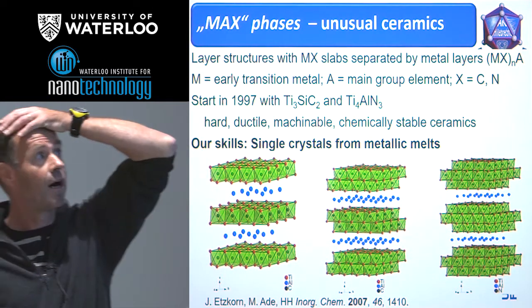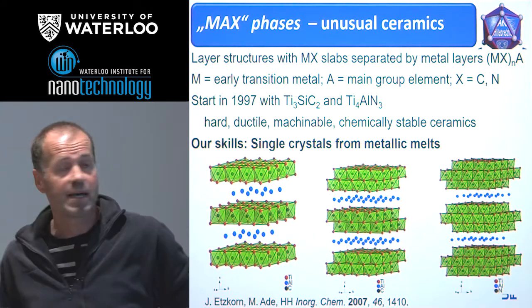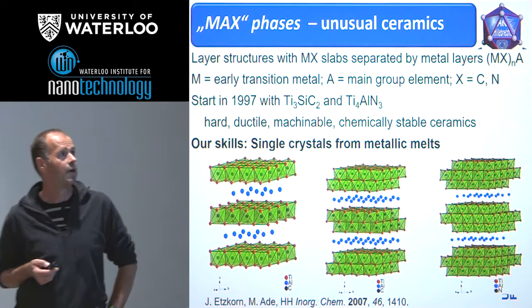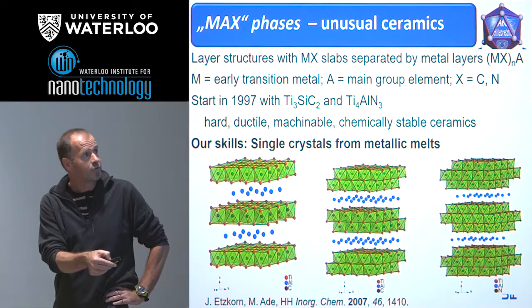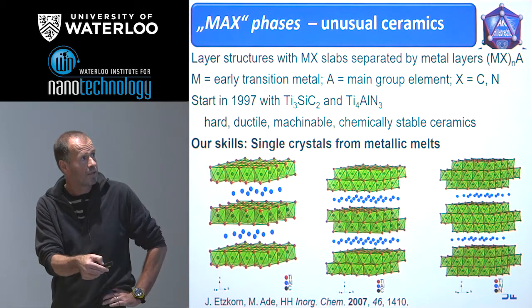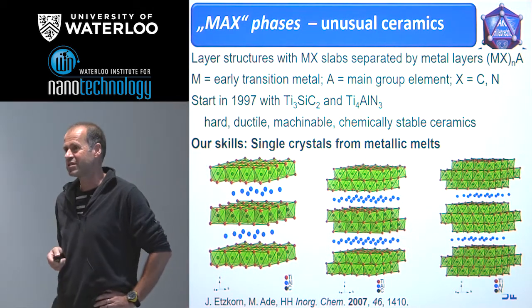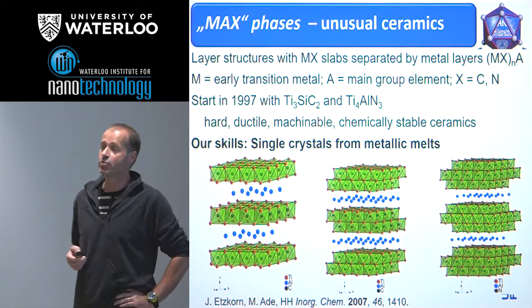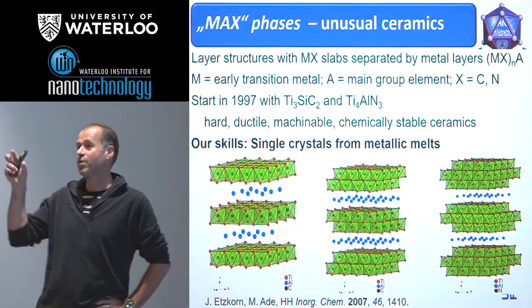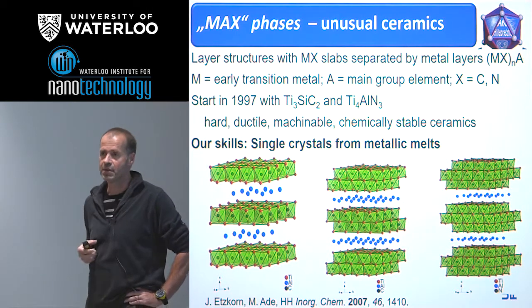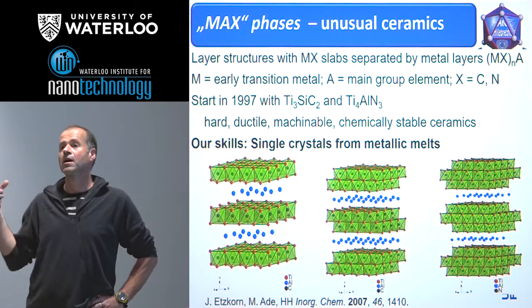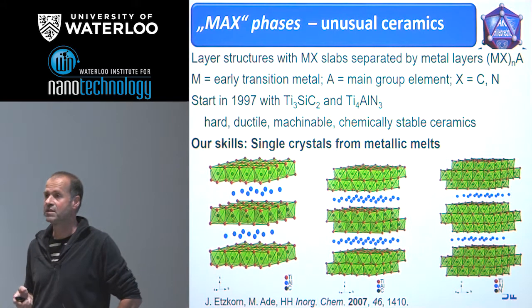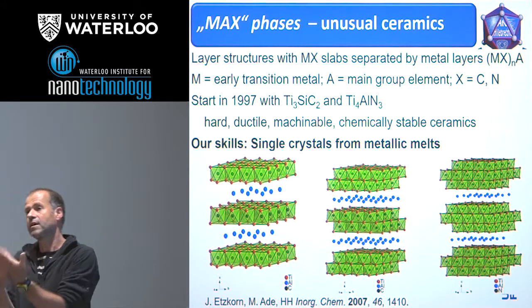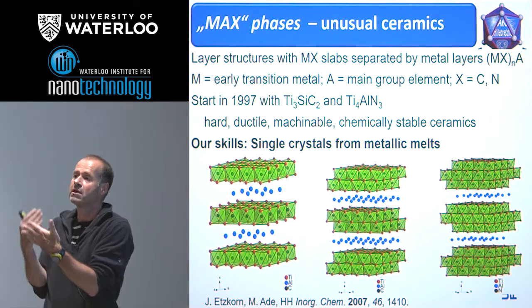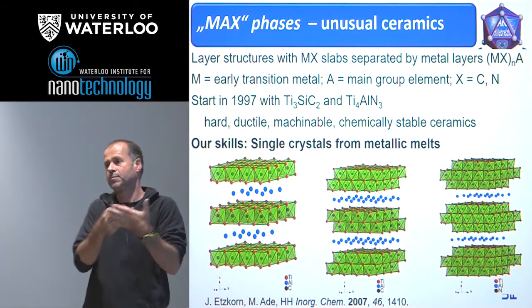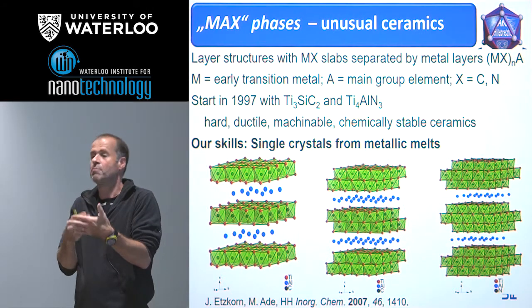The second last field are the so-called MAX phases. These MAX phases are meanwhile quite famous, because in the late 90s it was shown for titanium-3 silicon carbon-2 that this is a very special type of ceramics, because the properties are a positive mixture of the high temperature stability of ceramics and the machinable properties of intermetallics. That means the cracking of ceramics is always a problem, and you can avoid these problems by the combination with the typical properties of alloys or metallic materials.